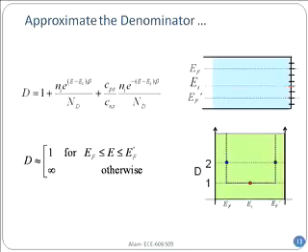Because think about a donor level, which is very close to the conduction band. In the donor level, the denominator is infinity. So surface recombination or any recombination will actually go to 0. The denominator is infinity, right? So therefore, a donor cannot be a recombination center. Had it been a recombination center, all electrons would immediately disappear through the donor levels. It's a very important point that you need to understand: even when you have 10 to the power 18 donors or acceptors, why is it that none of them participate in the recombination process at all? That was a question last time, right? Somebody asked this question. I was trying to explain it on the board.